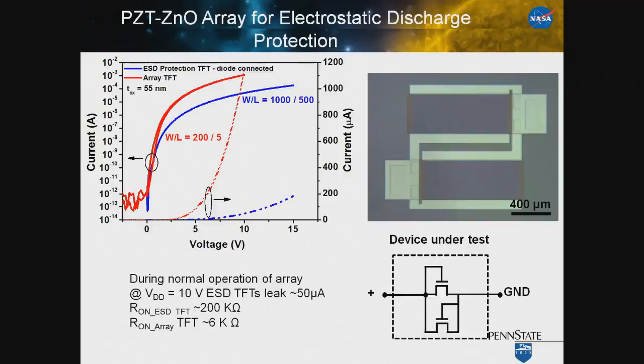We have also spent the last couple months working on electrostatic discharge protection of those devices, and so we have integrated on the mask pattern a much higher turn-on voltage thin film transistor, which is normally transparent to the system, so it's normally off, and so the voltage passes to the row column addressing. But if at any point there is a voltage spike that runs through the system, that zinc oxide thin film transistor and the protection circuitry shunts that voltage away from the higher sensitivity zinc oxide TFTs on the mirror element itself, and we believe this will significantly improve the final reliability of the device.